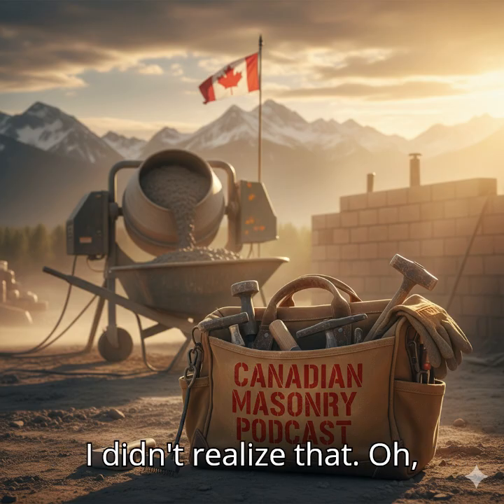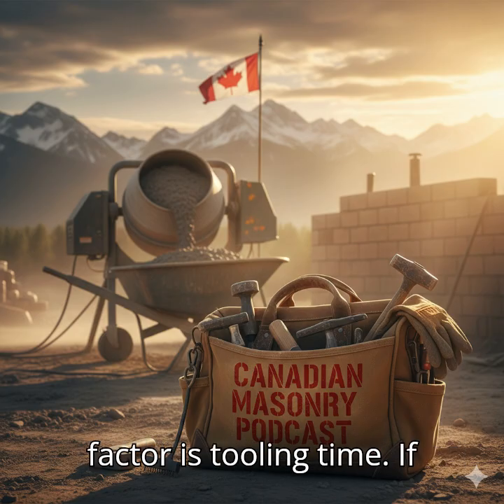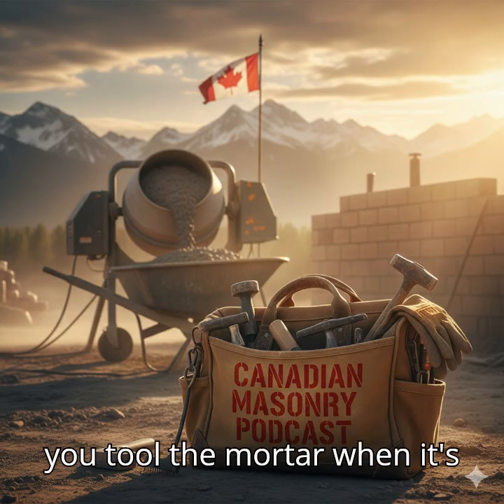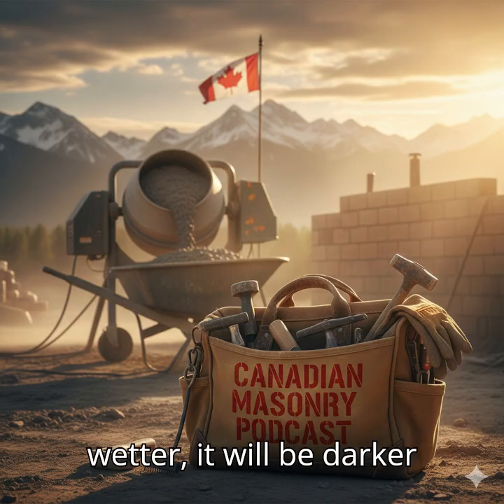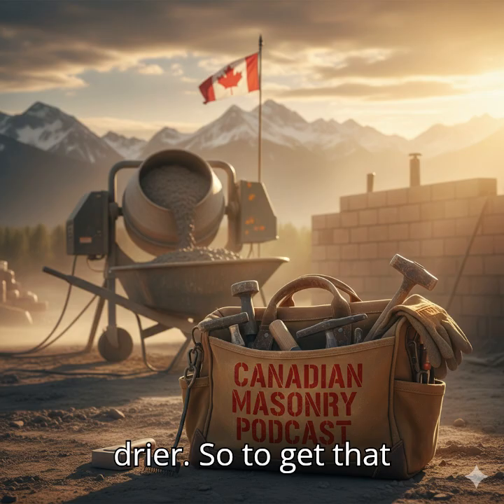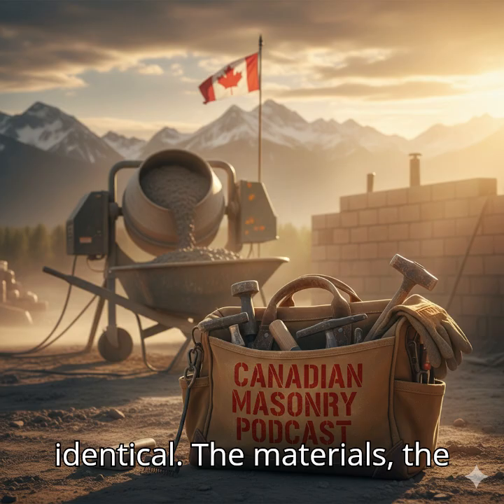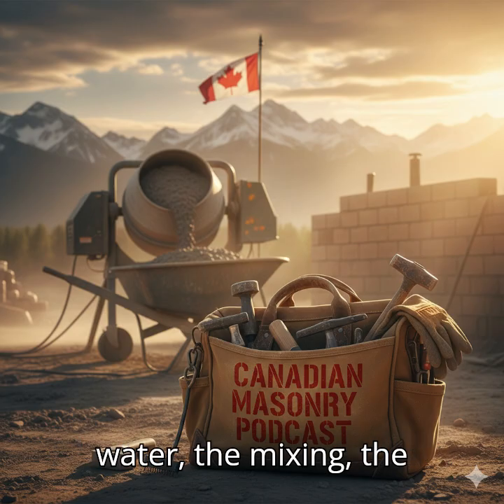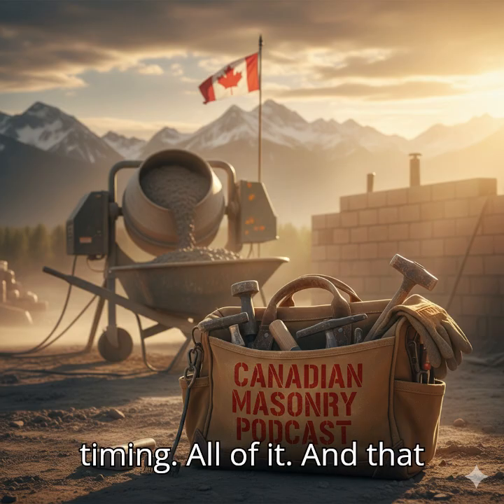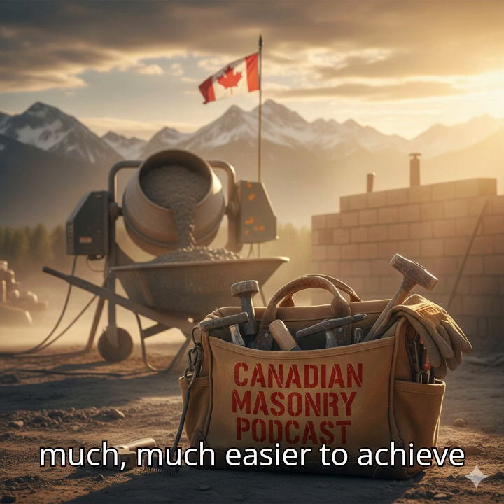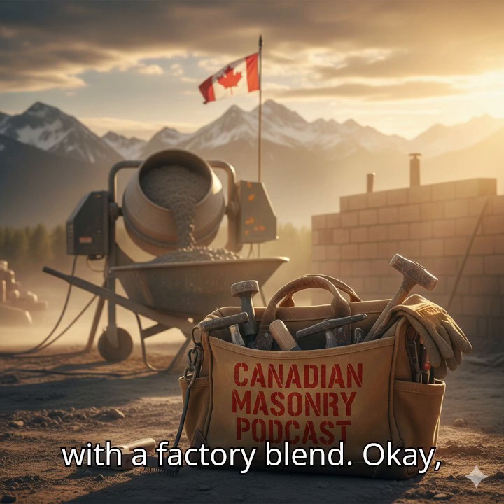I didn't realize that. Oh, yes. And the most overlooked factor is tooling time. If you tool the mortar when it's wetter, it will be darker than if you wait until it's drier. So to get that seamless, uniform look, everything has to be identical. The materials, the water, the mixing, the timing. All of it. And that level of control is just much, much easier to achieve with a factory blend.